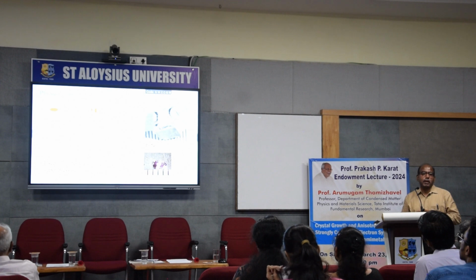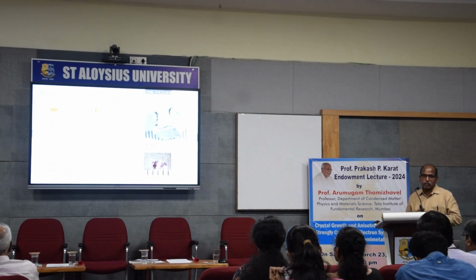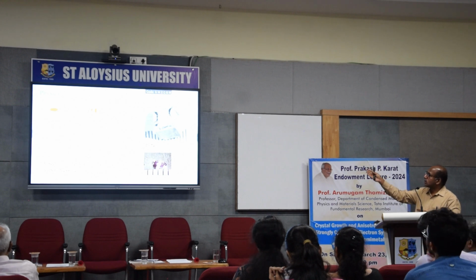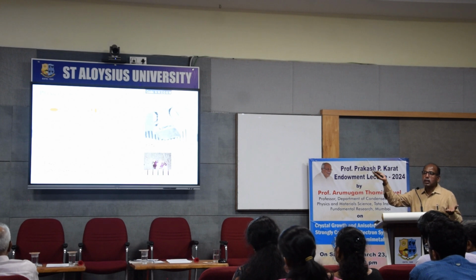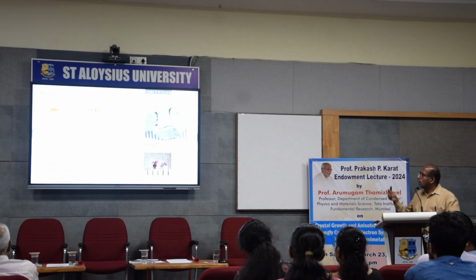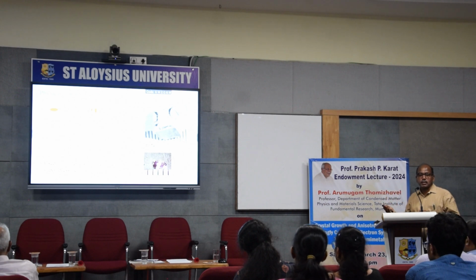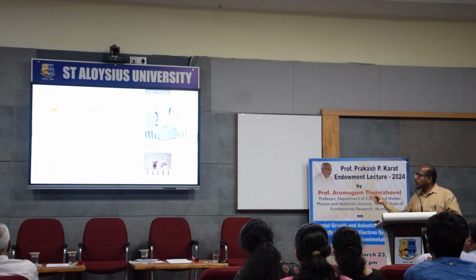Okay, then some of the crystals, they don't melt, they sublime. In those cases, we can take advantage of their sublimation, and we can grow these crystals by keeping them at two different temperatures, a hot zone and a cold zone. In the hot zone, the sample gets evaporated and gets transported to the cold zone, and you get single crystals by this process. This is called physical vapor transport. And sometimes you use a transporting agent like iodine, bromine, or something like that. This chemical transporting agent will also take the material from the hot zone to the cold zone, and you can get some crystals.